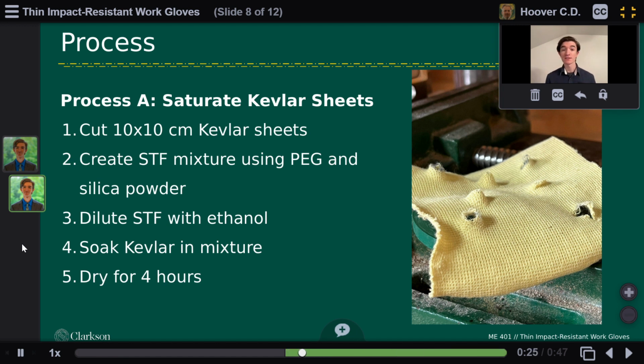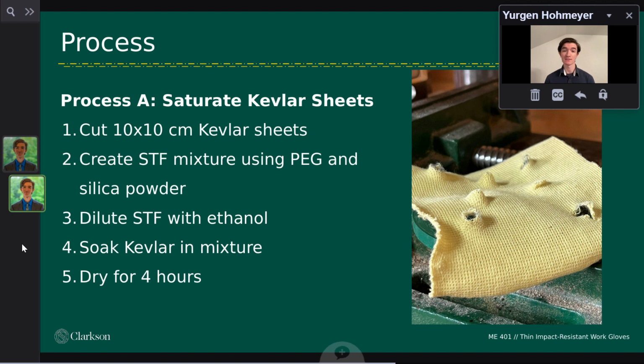The first step in the experimental process was to create the shear thickening fluid-saturated Kevlar sheets. This was done using polyethylene glycol, or PEG, mixed with silica powder. This STF was then diluted with ethanol in a 3-to-1 ratio to assist in impregnating the sheets with the STF. After soaking each sample for 1 minute, they were all air-dried for 4 hours.